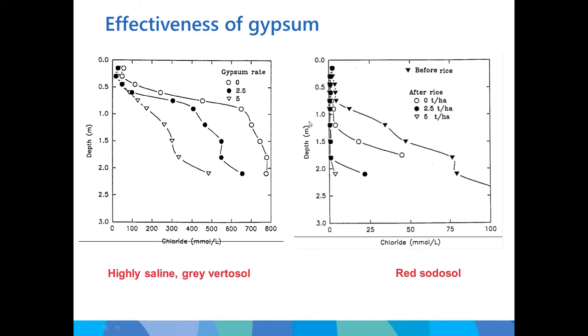This one is the results from that experiment, and there's a grey vertosol on the left and a red sodosol in the graph on the right. And you can see a zero gypsum rate, and you've got, we're going with depth, you've got quite high chloride. This is chloride, not electrical conductivity, but chloride's a good indicator of salinity. And you see that as you increase the gypsum rate from 2.5 to 5 tons with one rice crop, you get more leaching and you come down here. And so we've lost some salt there, a fair bit of salt, or chloride certainly.